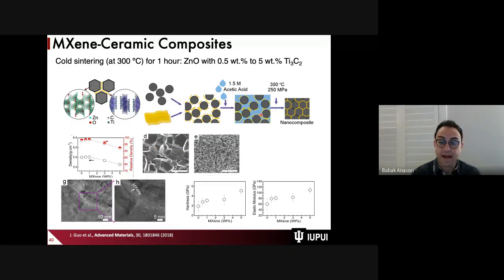The other advantage is by wrapping these MXenes around the grains of the ceramic, we prevent grain growth. So instead of having something like this during the synthesis, we keep the grains a lot smaller, because we don't allow the diffusion to happen by putting a MXene layer in between. And here's a transmission electron microscopy image that shows that we can indeed put MXene flakes at the grain boundary. By doing that, we can improve hardness, and the modulus measured by nanoindentation also showed some improvement. So this is in ceramic composite.